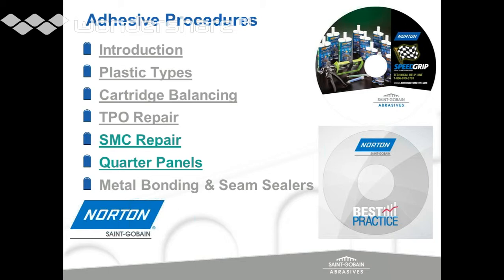Matter of fact, when they bead out the damaged or repair area, they use 36 grit on the little grinder that you saw, or 50 grit depending on how soft the plastic is. Maybe use 50 grit with a fiberglass repair, and then they used 80 grit on a DA. So it still follows that general rule of thumb that the glue needs some type of 36 to 80 grit scratch to bite into.